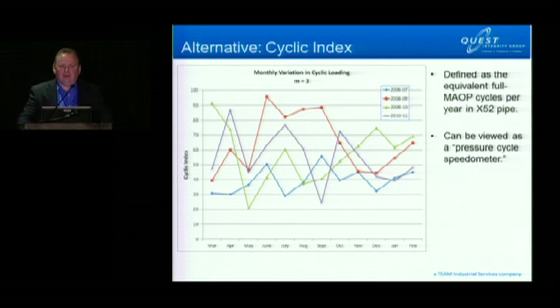An alternative that we've recently come up with is a cyclic index, which is a single number. The full definition of it is an equivalent number of cycles per year that are full MAOP, 72% SMYS, but tagged to X52, because as I said earlier, you can't normalize the hoop stress by the SMYS in fatigue calculations. You have to take the absolute hoop stress. So we just picked X52 as just a marker, yet we had to draw a line in the sand somewhere. And you can view this number as a pressure cycle speedometer.